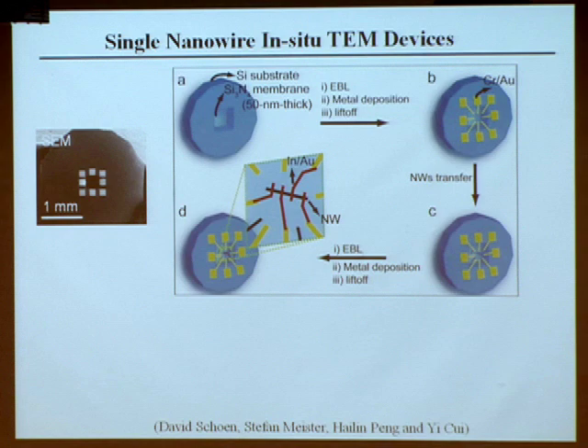And here's the device we made. This has a really thin silicon nitride membrane, really transparent to the high energy electron beam, about 50 nanometer also. We made our nanowire device on top of this membrane. So you can throw down a nanowire and then you make multiple electrical contacts.